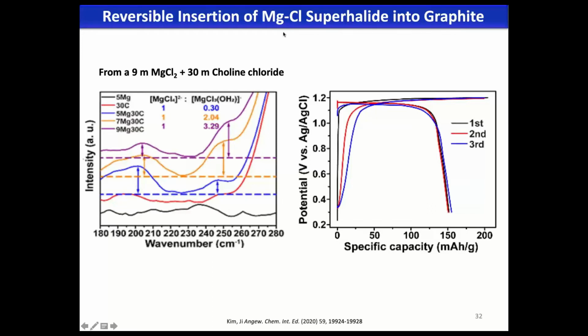Here we inserted magnesium chloride superhalide into the graphite structure, and we can have some nice charge and discharge of graphite, although the Coulombic efficiency should be improved, hopefully. But we have some nice reversible chloride storage in graphite in aqueous electrolyte. We use this electrolyte that effectively suppresses the oxygen evolution and also chlorine evolution. Chlorine evolution will be quite severe if you have a purely concentrated chloride electrolyte. And we collaborate with Dr. Fang at OSU, and you can see the evidence of the superhalide charge carrier. I don't have time to explain that in detail. Please read our paper if you're interested.